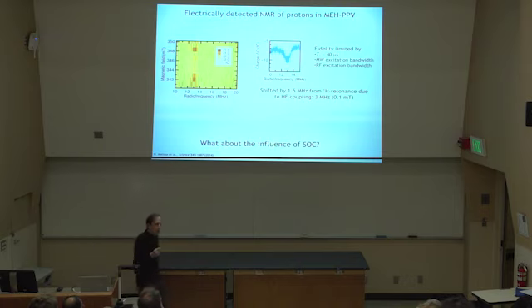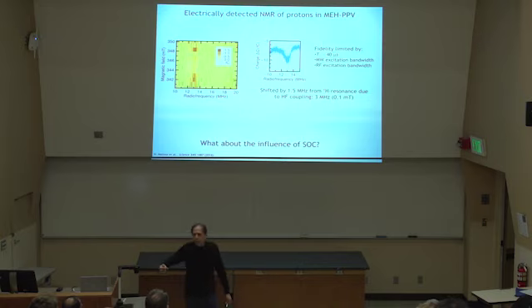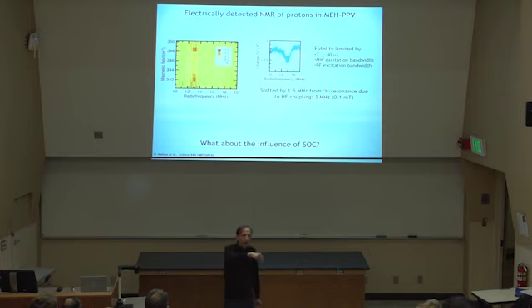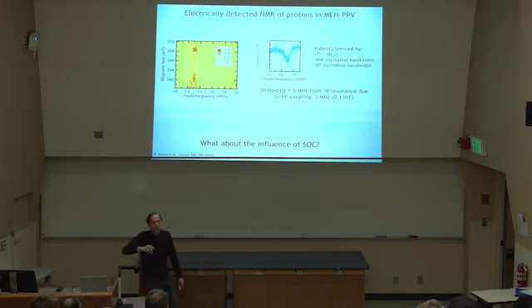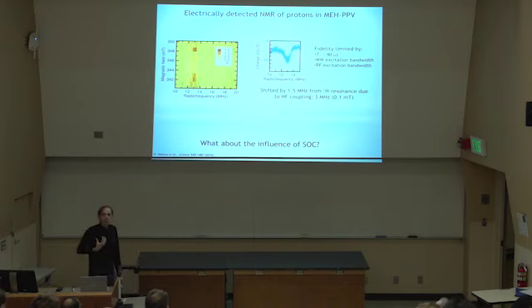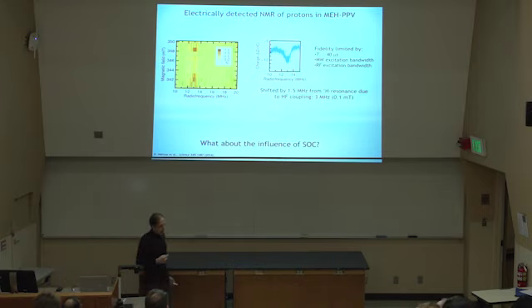And where spin-orbit coupling really influences magnetic resonance, or let's say electron paramagnetic resonance, is by means of the Landé g-factor, the deviation of the effective Landé factor that we detect here relative to the vacuum Landé factor of 2.0023 something that comes out of QED, basically. So now we're in the business of measuring g-factors. The problem is, if you have any sort of disorder or complexity in your material, that will be distributed. That's actually called g-strain, the random distribution of g-factor deviations.